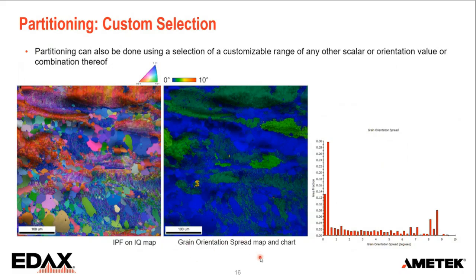So how much deformation do we have inside each of the grains that is specified? And we can quantify that in a chart. Now, in this chart, we can recognize that there is some kind of cutoff at about half a degree orientation spread. Over that, it's almost horizontal, this deformation distribution, to about 10 degrees. But below it, there's a big spike of points from grains that have very little deformation.